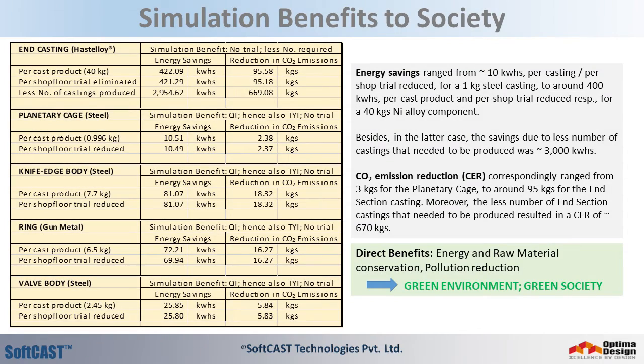These case studies also show the considerable benefits that accrue to society due to the optimization of casting manufacture through SoftCAST. Energy savings ranged from 10 kWh to 400 kWh per cast product and per shop trial reduced, for the 1 kg planetary cage and the 40 kg nickel component respectively. Besides, in the latter case, since less number of buffer castings needed to be produced, there was a saving of 3,000 kilowatt-hours.